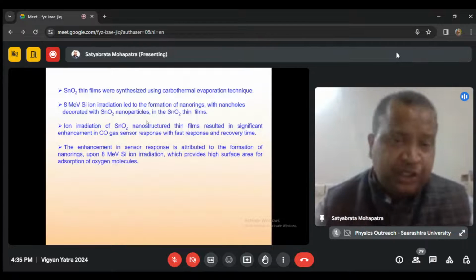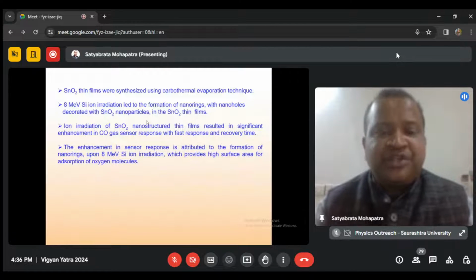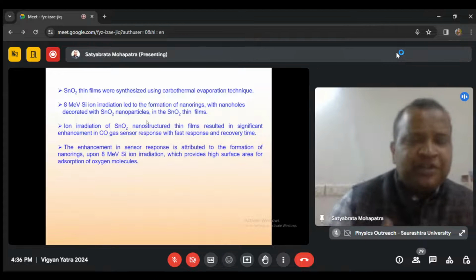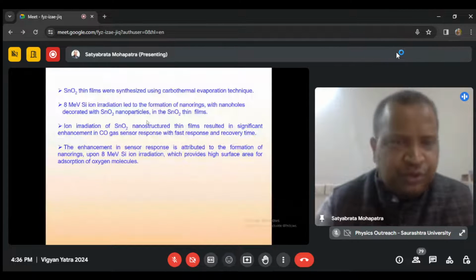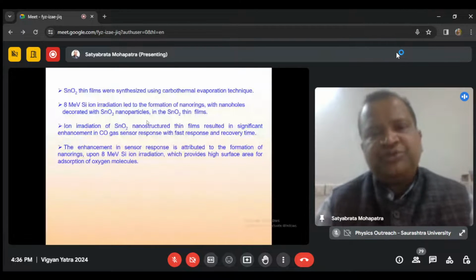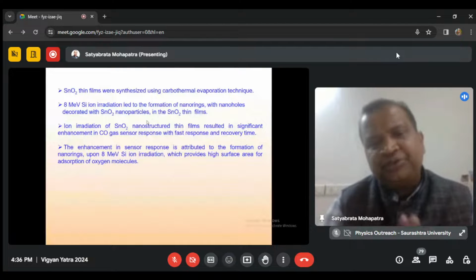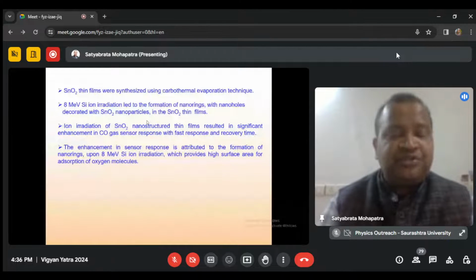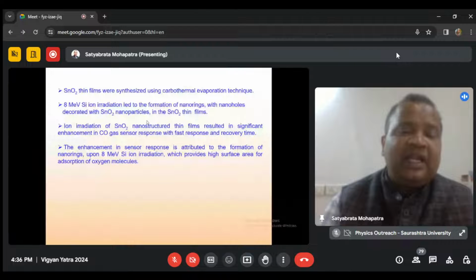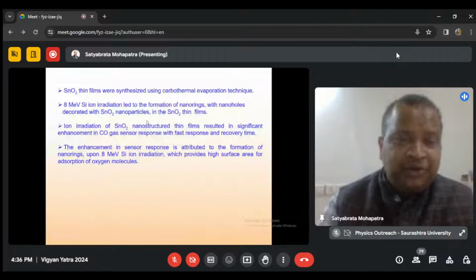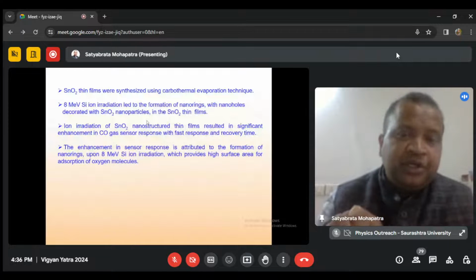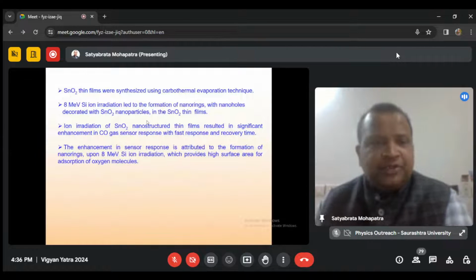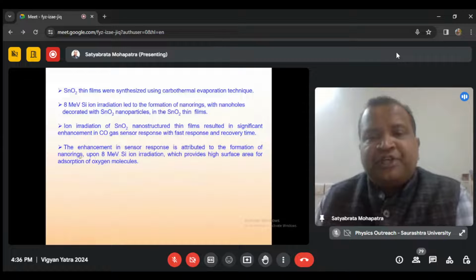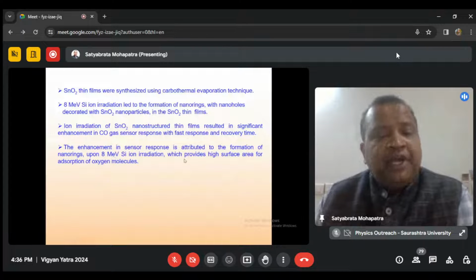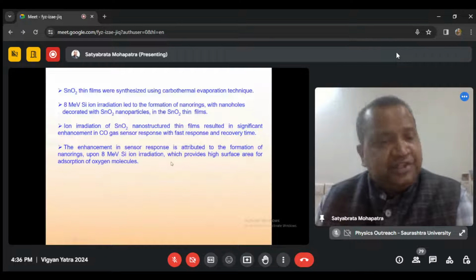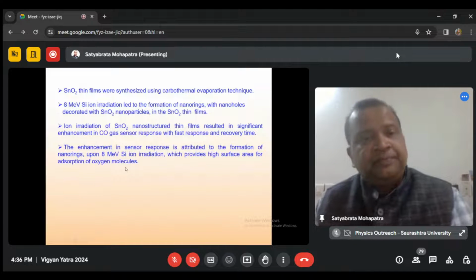That's what is required. You can always improve. There is always room for improvement in science. What is important is that there is a very simple tool: you optimize this defect concentration, or what we call oxygen vacancy concentration. You should tune structures which are two-dimensional, and you adequately dope, or you create porosity in these nanostructures. That's the way. And that's where you see that the enhancement of sensor response is attributed to formation of nanorings upon 8 MeV silicon irradiation, which provides high surface area for adsorption of oxygen molecules.